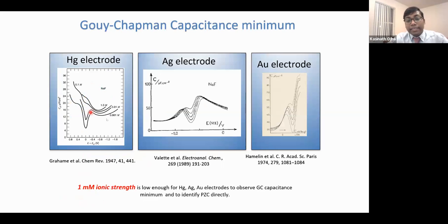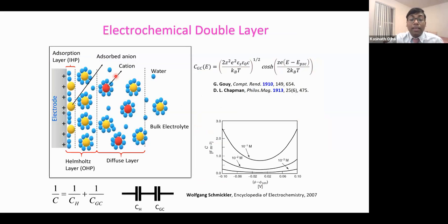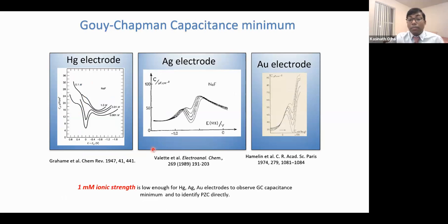Now, in all these cases, 1 millimolar ionic strength was low enough to find a capacitance minimum. But in electrochemistry, you know which metal is most used? It's probably platinum. Everybody uses platinum as an electrode and a catalyst. But for platinum, we never saw those capacitance minima. Those capacitance minima tell you about how the diffuse layer is arranged in the double layer structure. So from those capacitances, we can actually tell about the double layer structure of the electrode. But in the case of platinum, we never really found those minima.